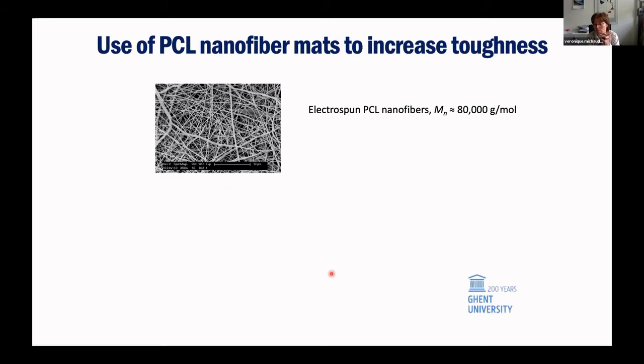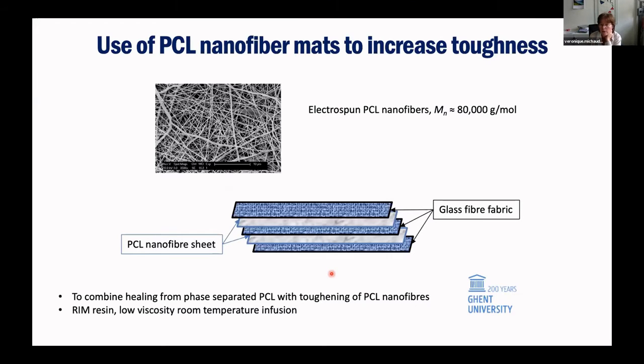Then we decided that, okay, the toughness issue is linked to the microstructure size. And we had discussions with our colleagues from Ghent University, Wim Van Paepegem and Karen De Clerck. They've been working a lot on electrospun nanofibers, and they showed beautiful results at some conferences that with the nanofiber mats, you increase the toughness tremendously. So we made a small collaboration with them and used electrospun PCL nanofibers, which they produced for us. We integrated them into the glass fiber fabric as an interlayer between the fabric.